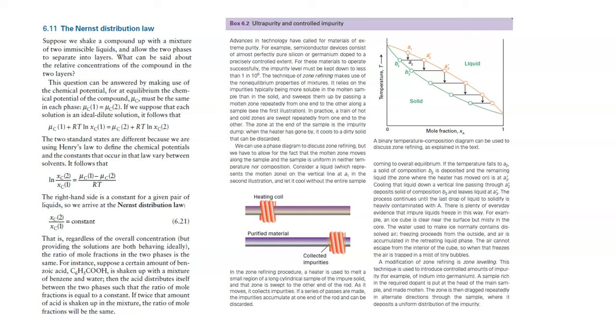It relies on the impurities typically being more soluble in the molten sample than in the solid, and sweeps them up by passing a molten zone repeatedly from one end to the other along a sample. In practice, a train of hot and cold zones are swept repeatedly from one end to the other. The zone at the end of the sample is the impurity dump. When the heater has gone by, it cools to a dirty solid that can be discarded. We can use a phase diagram to discuss zone refining, but we have to allow for the fact that the molten zone moves along the sample, and the sample is uniform in neither temperature nor composition.